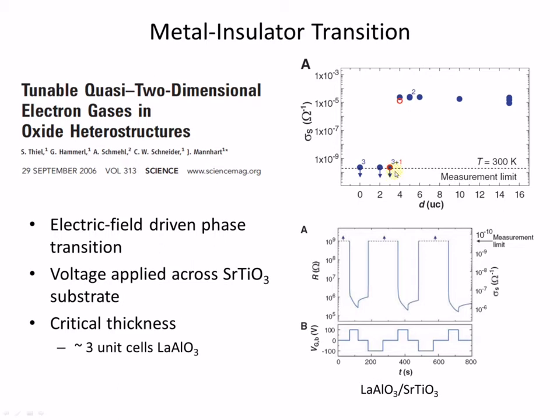These red circles indicate that in fact the 3 unit cell structure was bistable, in that it could be either conducting or insulating depending on the prior voltage applied from the back of the strontium titanate substrate. So in a subsequent experiment, they could begin with an insulating interface. Here we're plotting resistance now on a log scale, and by applying 100 volts to the back of the strontium titanate, they could then switch the interface to the conducting state, and when they turned off the voltage, it remained conducting. And they could switch it back to the insulating state by applying minus 100 volts.